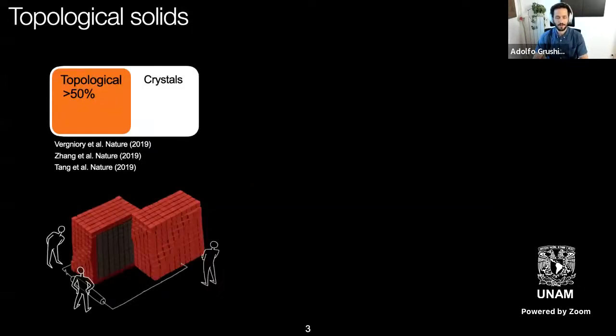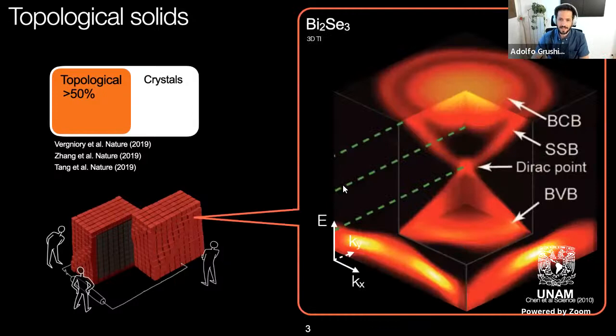In fact, one reason you should care about topological solids is because more than half of the materials we know exist are predicted to be topological solids, at least at the Fermi level. Even if you count bands that are not at the Fermi level, the percentage goes even higher. And what this means is that these materials are, as I say, insulating in the bulk, and in the surface, if we look at how electrons disperse, they have this dispersion relation that looks like a cone, or a Dirac cone, and it means that it's gapless, and that means that it's metallic.